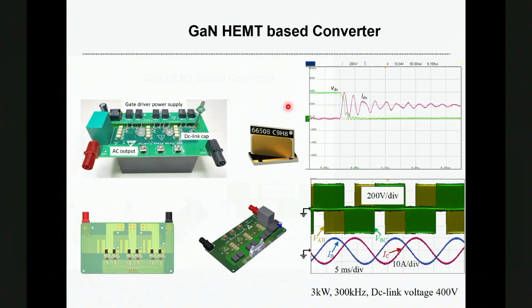This slide shows a gallium nitride-based three-phase DC to AC inverter. As you can see, the gallium nitride devices can finish a switching transition within 10 nanoseconds, very fast switching. Here we have also demonstrated 3 kilowatt, 300 kilohertz operation of that DC to AC converter, and the DC link voltage is 400 volts.